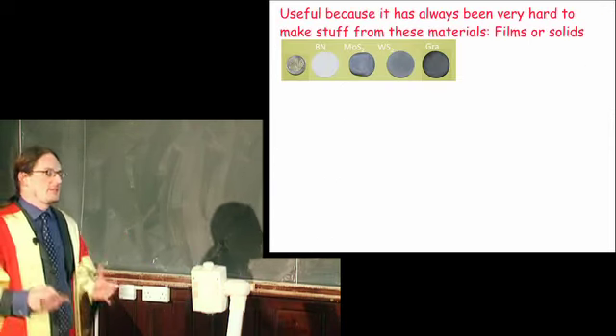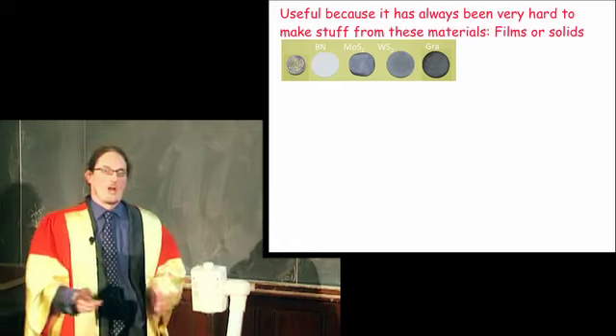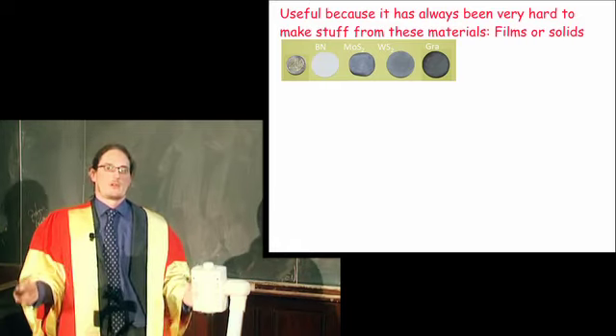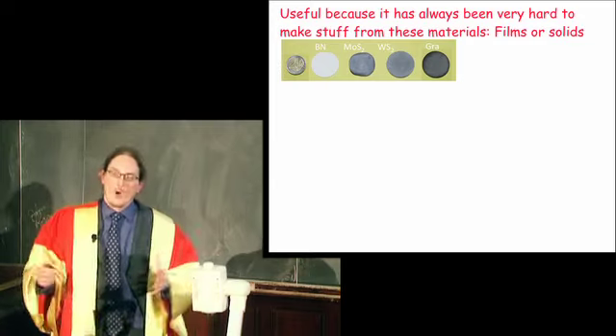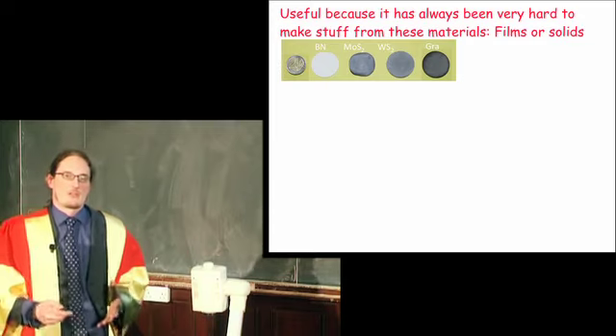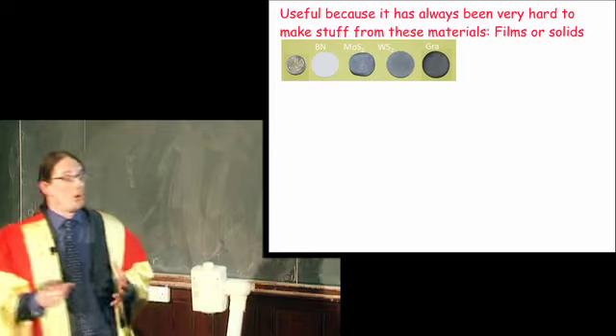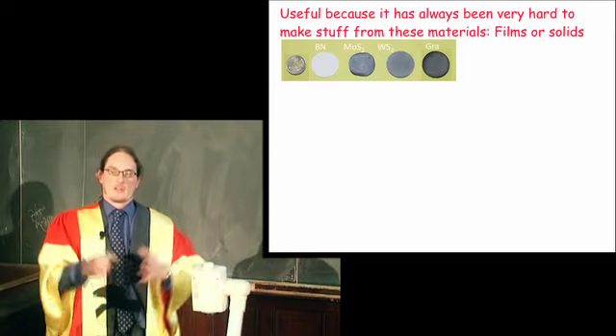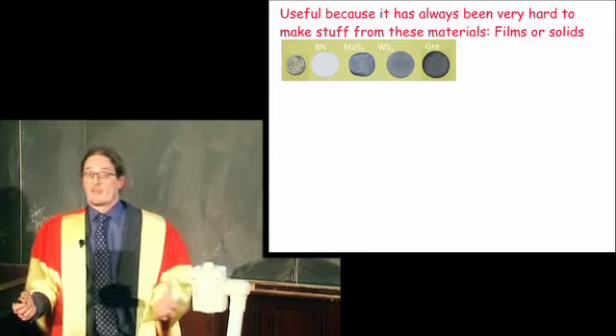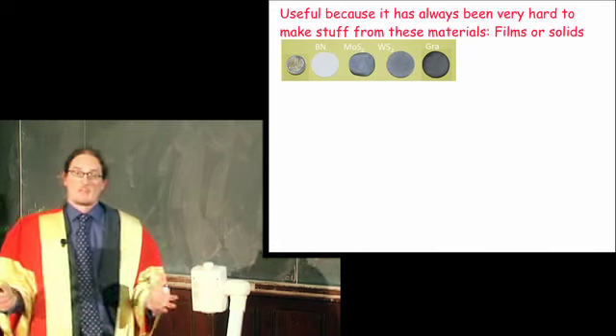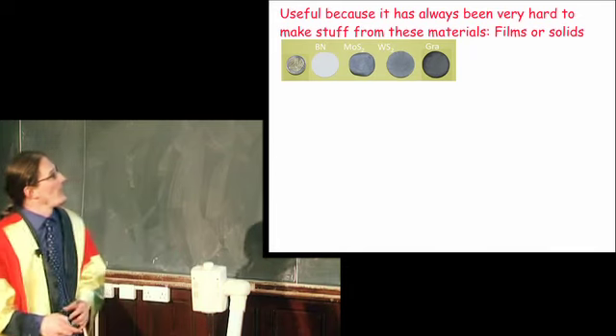Now, one of the reasons this is important is that people have known for a long time that these layered compounds were useful in a number of applications, but one of the problems was that they're very, very difficult to process. So, for example, boron nitride can be formed into structures, but at temperatures of about 1,000 degrees centigrade. So, obviously that can be done, but it's not straightforward.